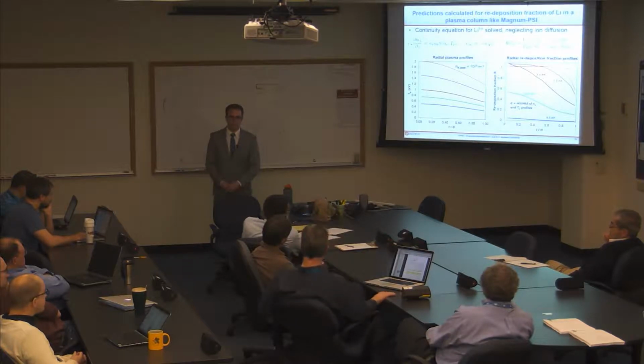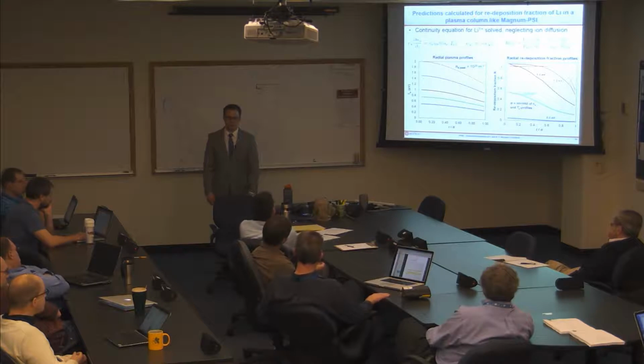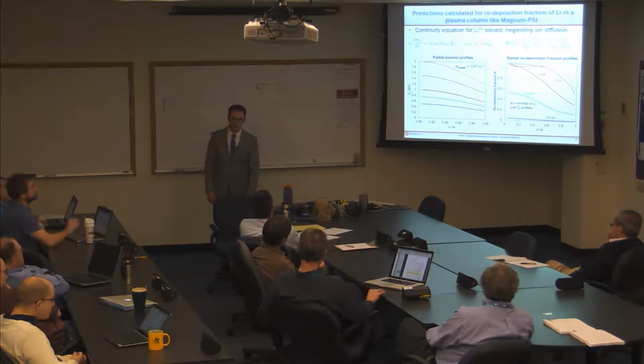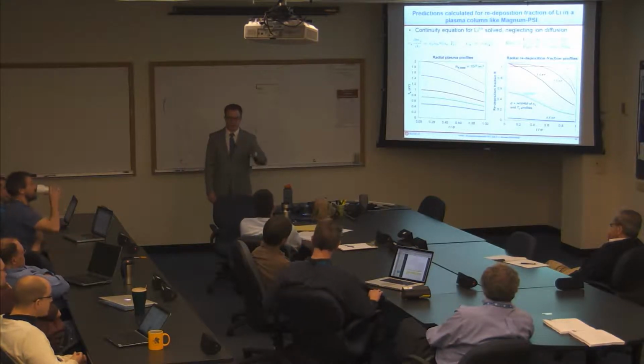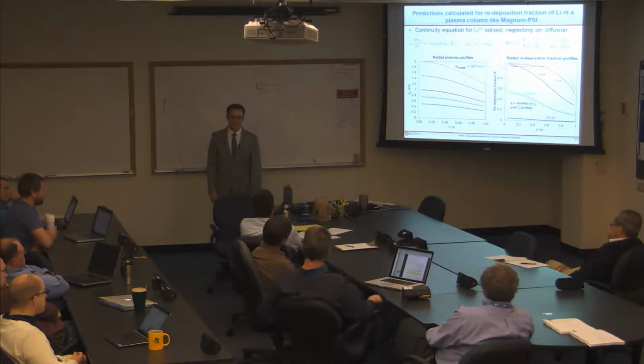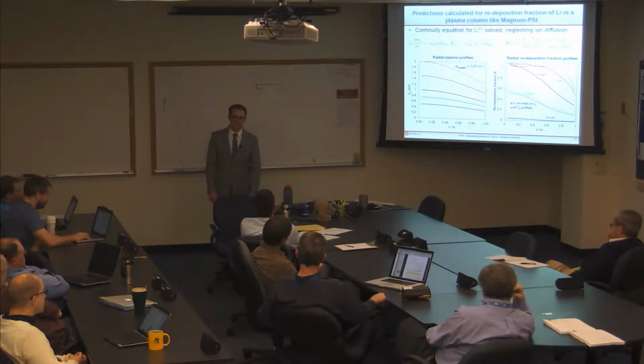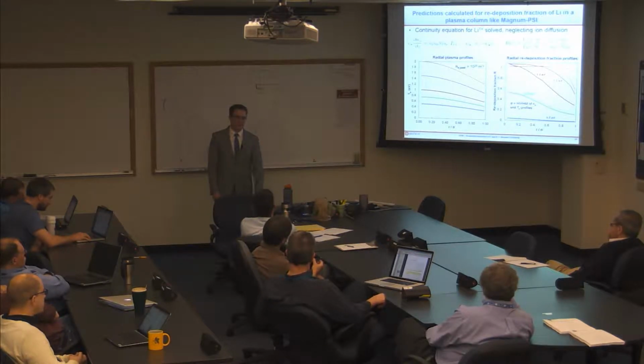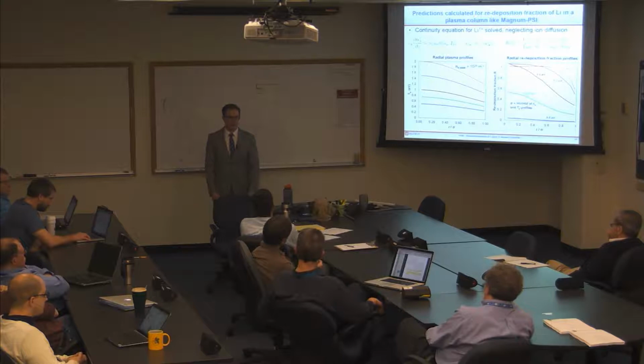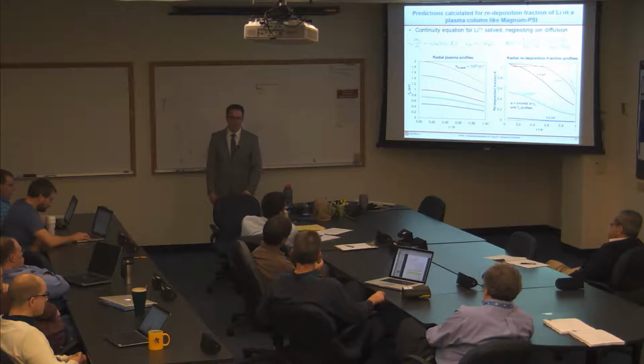No. So what do you mean by thermalize? It has the same temperature? It has the same velocity as the deuterium ions that are streaming back to the surface. So this is actually an effect that they measured in Pisces. They looked at the Doppler shifts of some impurity, I think it was beryllium, in a deuterium plasma, and they see that it actually picks up the velocity of the streaming deuterium ions as it goes back to the surface. But we didn't measure that directly here, so that's an assumption.